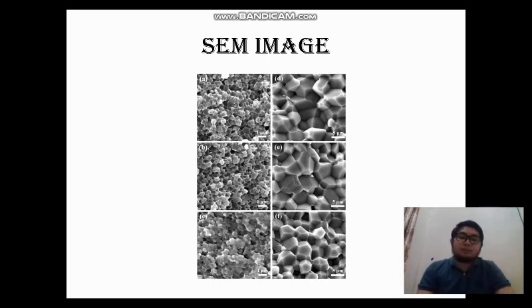As you can see in the figures, 1%, 3%, and 5% calcium fluoride with aluminum nitride sintered at 1800 degrees Celsius. It is distinguished to find that grain growth is suppressed with increasing calcium fluoride content which is in good agreement. While grains in the sample with 1% calcium fluoride have developed into a hexagonal shape, as you can see in figure A, most grains in the sample with 5% calcium fluoride still keep their initial shape fairly.